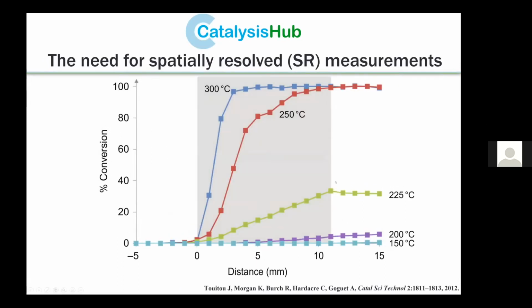As you can see here, for example, for CO oxidation, although 250 and 300 degrees look exactly the same to a normal user who looks just at the end-pipe measurement, if you look at the concentration of the gases, the conversion in this case, at various positions, you see that at 300 degrees you get pretty much 100% conversion already at 3 millimeters in, whereas at 250 you only get it toward the end, which will make the analysis fallacious.